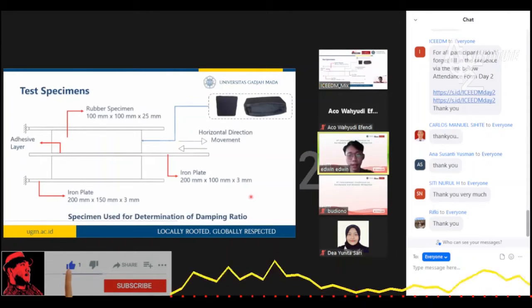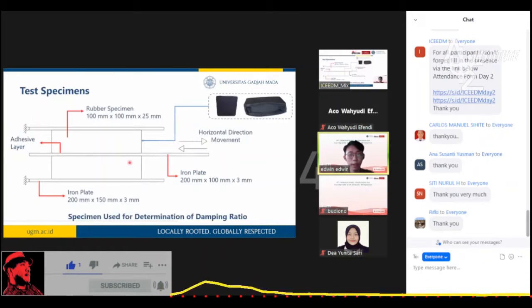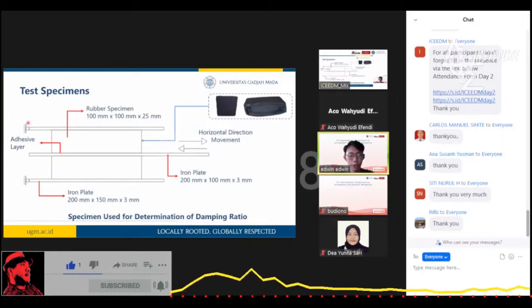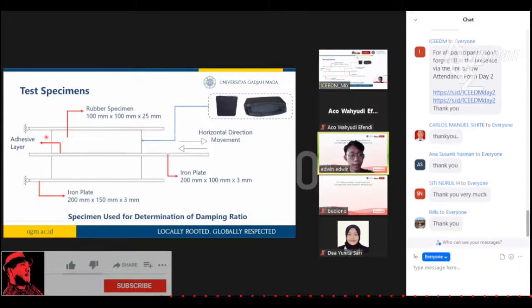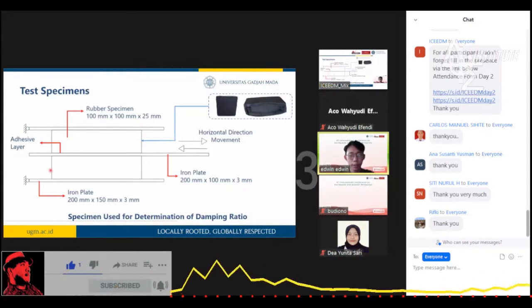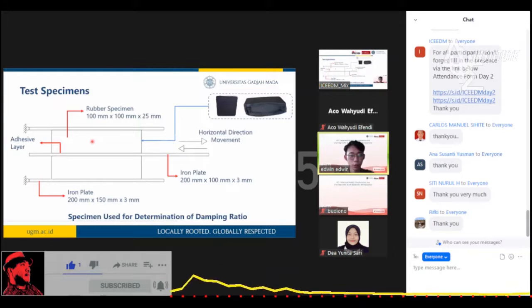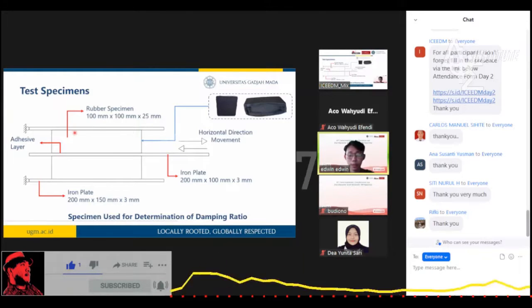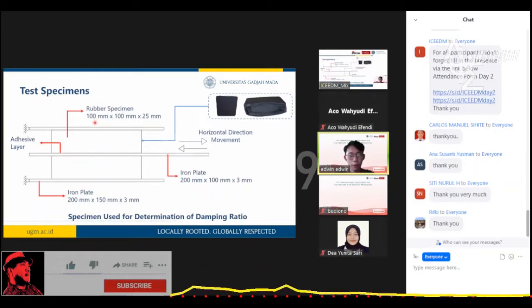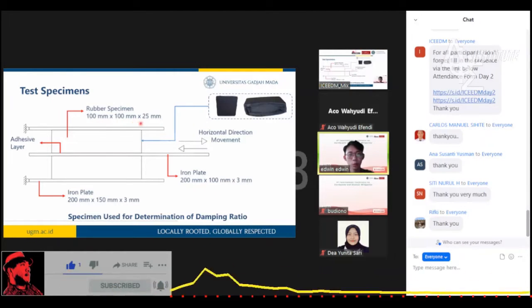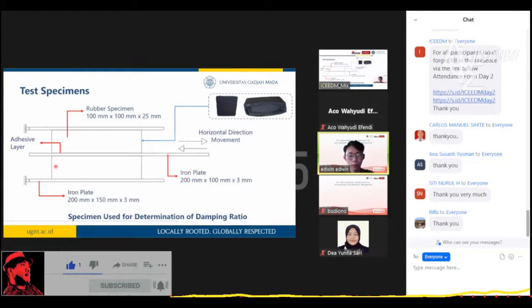After the tensile test and hardness test, there was also damping test. And this is the specimen used for determination of damping ratio, as we can see in the figure. It was made into a model resembling viscoelastic damper using two pieces of rubber specimen with dimension of 100 millimeters times 100 millimeters times 25 millimeters that was glued to the iron plate.